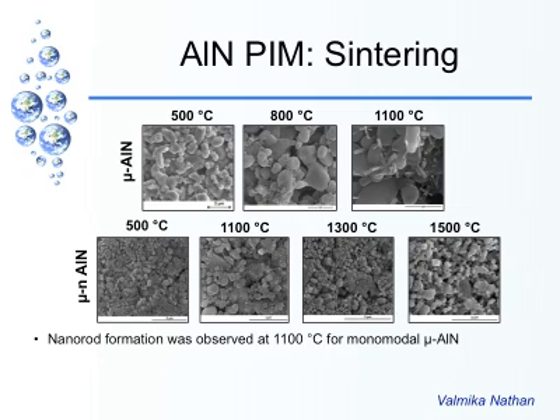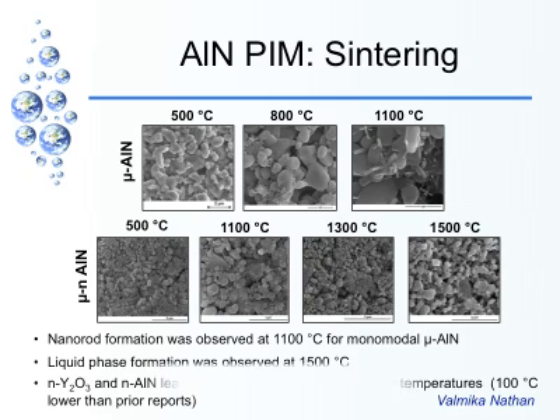Okay? The main thing was this nanorod that we could see in the micro scale, we could not see in the micro-nano mixtures. And it is possible that the capillary effects end up holding the liquid very tightly and limit some of the reprecipitation. Either that, or a lot of aluminum nitride in the nanoscale begins to dissolve easily into the liquid, and so maybe some of the nanorod formation is suppressed. Okay. But the main thing was liquid phase was forming at a temperature that was about 100 degrees lower than what anyone has reported earlier. Okay, so we could see it at 1500, and maybe it occurs a little bit earlier, and that's some thermal analysis that we have to do to find that out.